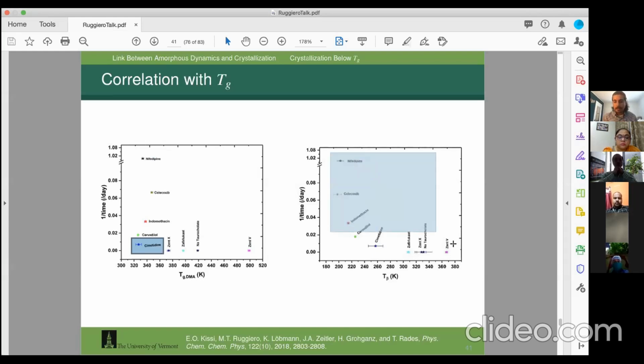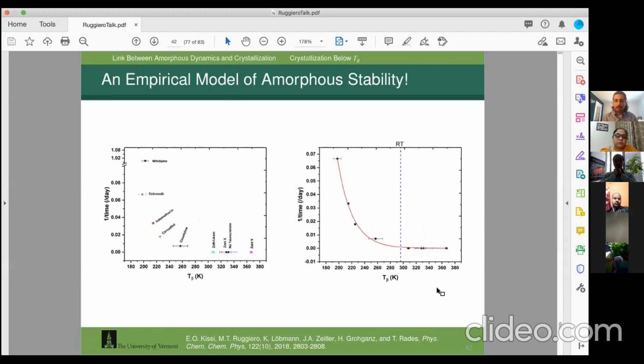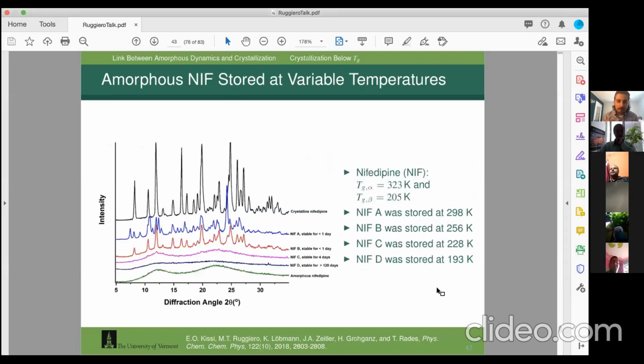On the other hand, if we plot the stability as a function of the beta temperature, where these types of motions are frozen out and aren't allowed to happen, we get a clear correlation. We proved this was true by taking that really unstable material, nifedipine, and storing it at temperatures slightly above and below that secondary glass transition temperature.